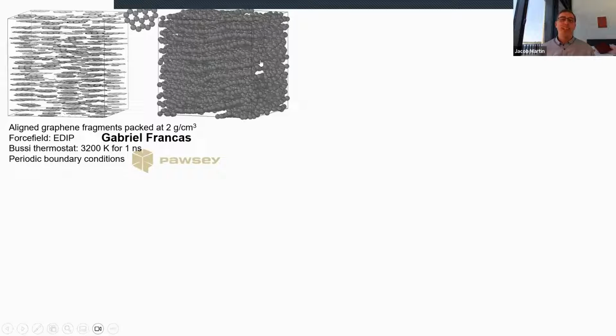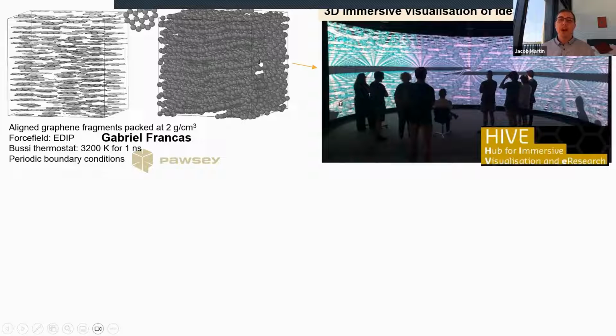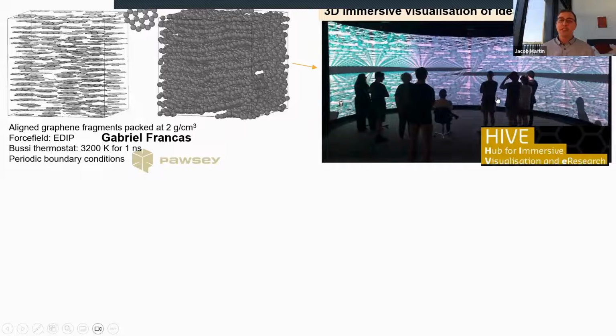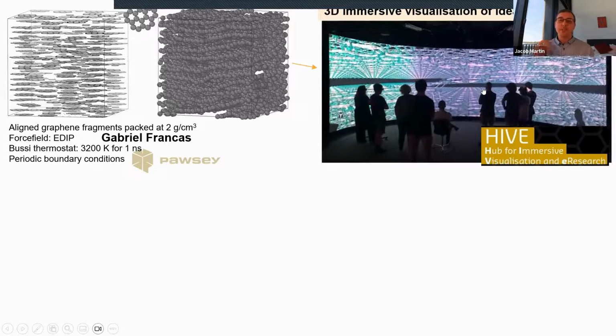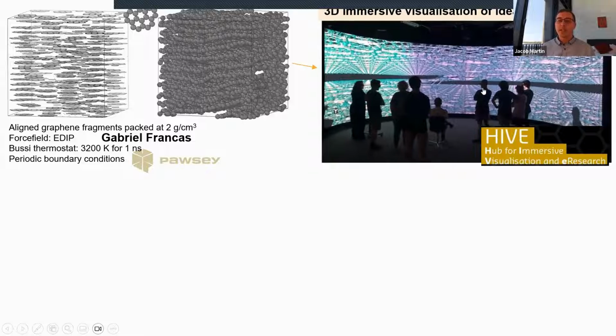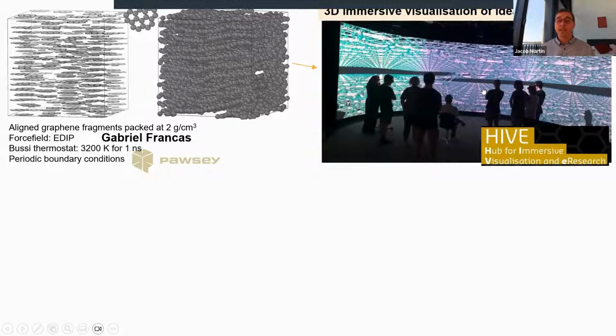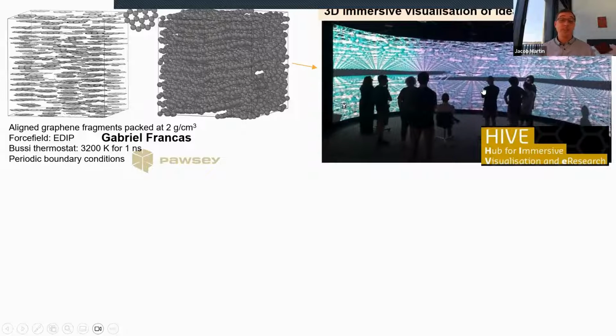And I was talking to my colleague, and he just didn't think there were any screws in this. And it was very hard to actually visualize it in 2 dimensions. And so what we did is we called up the Hive, which is Curtin University's visualization studio, which has this beautiful 180-degree cylinder display, full 3D, with stereoscopic glasses. And the whole group came down. And the first thing that we did is we looked at some idealized screws so that we understood what they look like. And then we put in our models, and we were able to see these screws.